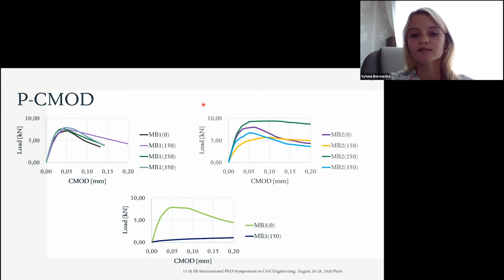These figures show the maximum load as a function of the crack mouth opening displacement. The ductile behavior of the MB3 series concrete after 150 freeze-thaw cycles was shown. The addition of basalt fibers in the cement matrix caused the elongation of the deformation segment until the maximum load is reached. The nature of the work of concrete with the addition of fibers in the cement matrix is clearly changed from quasi-brittle to quasi-plastic, and it is shown by the elongated shape of the MB2 and MB3 series curves